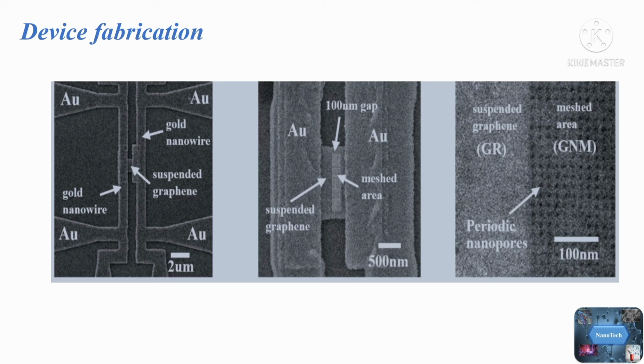They successfully observed the thermal rectification on suspended graphene devices at both 150 and 250 Kelvin. The nanopore diameter is about 6 nanometers, and the pitch is about 20 nanometers. Heat flux measurement is not disturbed by the leakage of electron current through the suspended channel when using the differential thermal leakage method.